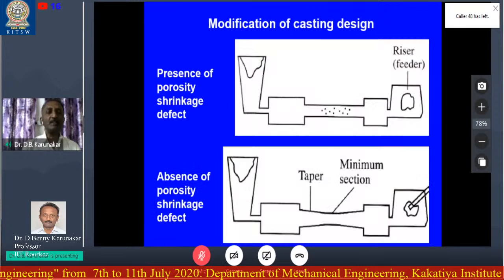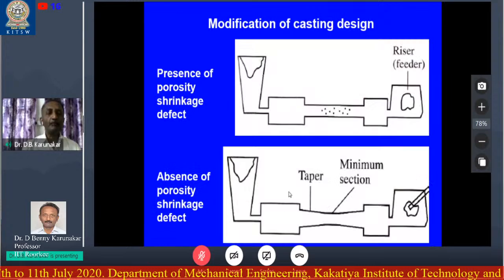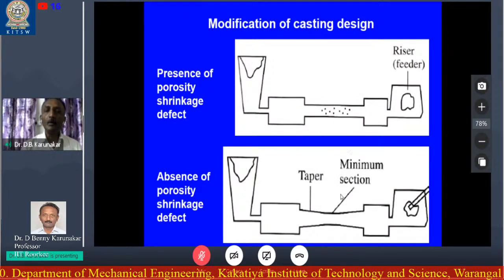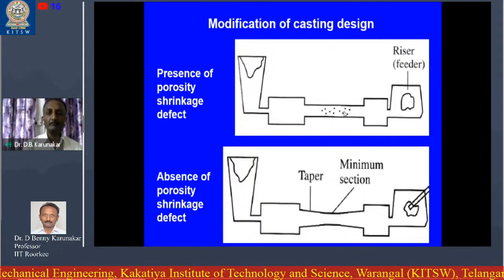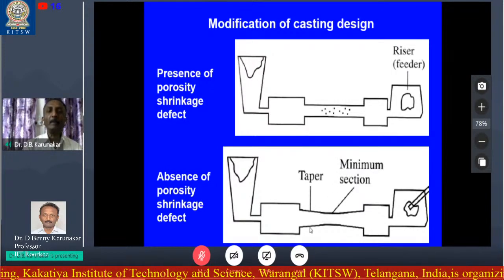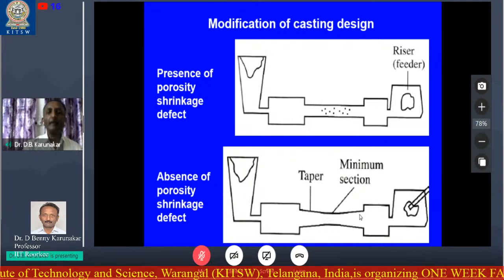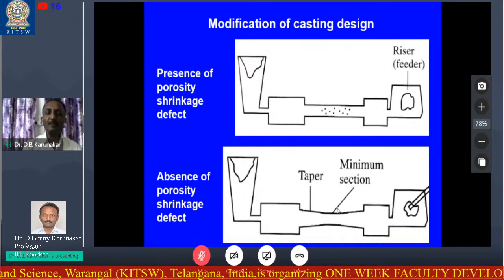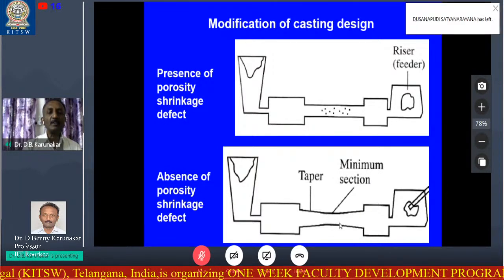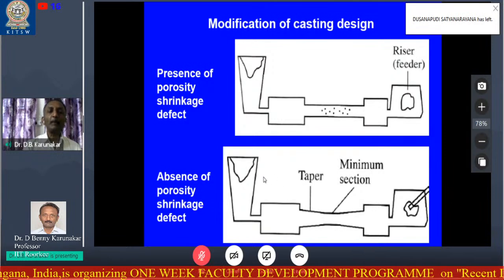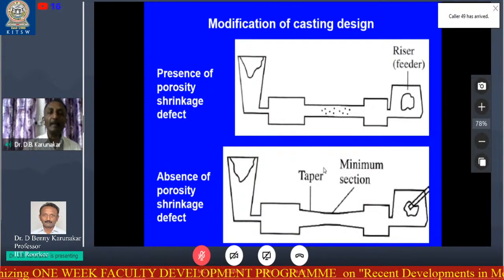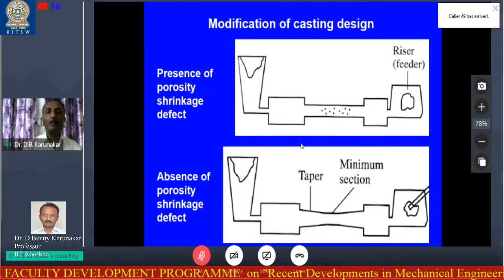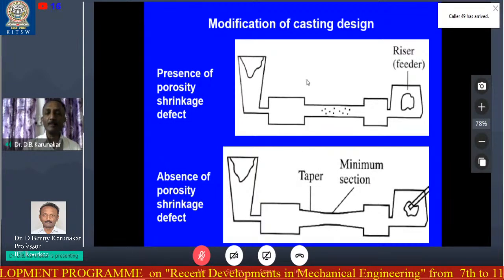Modification of the casting design: here we have made a taper. There was no taper here. So by making a taper, what we have done is initiate the solidification here, and the solidification propagates. So by making the taper, we are able to achieve directional solidification.